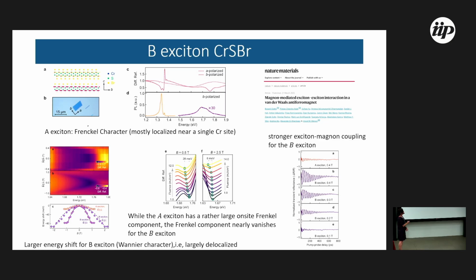This B exciton is different from the A exciton. The A exciton is more localized, and the B exciton is less localized. The shift of energy when you probe this phase transition is much more important in the B exciton, and the B exciton is also more coupled with magnons. People published this year, in March 2025, that it's more coupled, and you can see clear oscillations of the energy of the excitons. They also show several things that are more important for the B exciton compared to the A exciton. This is very nice work performed in the group of Vernon.